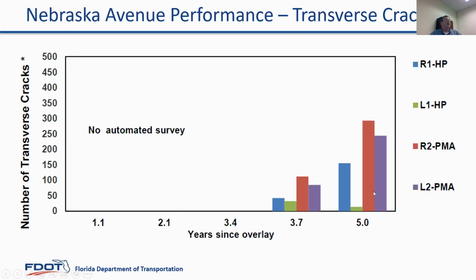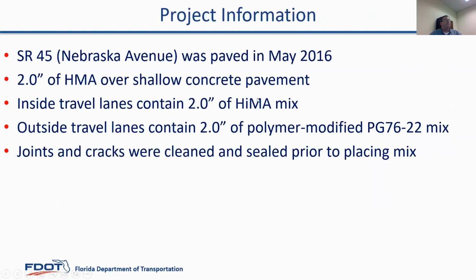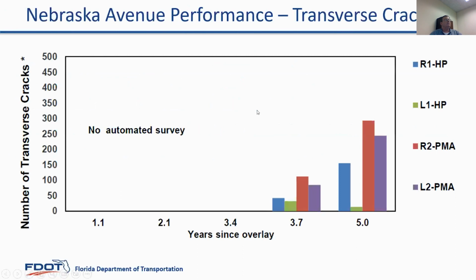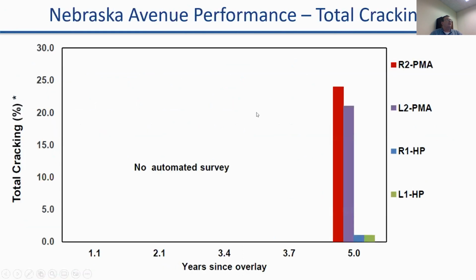And these are the number of transverse cracks. You're seeing one lane with almost no transverse cracks with the HiMA, and then the other lane's got about half of what you're seeing in the 2 conventional lanes. Now, if you go to percent cracking on the next slide... There we go. So total percent cracking, now it's really significantly different.